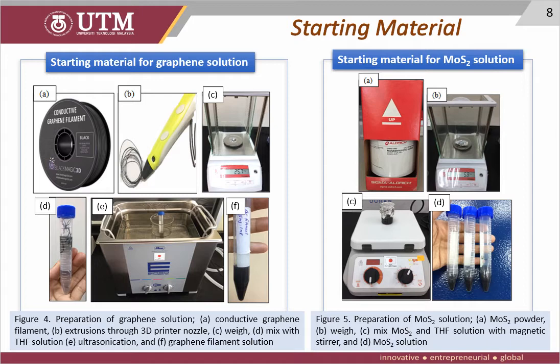Here is more detail on the starting material for graphene and MoS2 solution. We use conductive graphene filament, which is extruded through 3D printer nozzles, and we mix it with tetrahydrofuran, THF, solution and undergo ultrasonication until the solution disperses homogeneously to become the graphene filament solution. For MoS2, we use MoS2 powder purchased from Sigma-Aldrich, and without any further purification, we mix it with THF solution also using a magnetic stirrer, and finally got the MoS2 solution. All of this is done at room temperature.